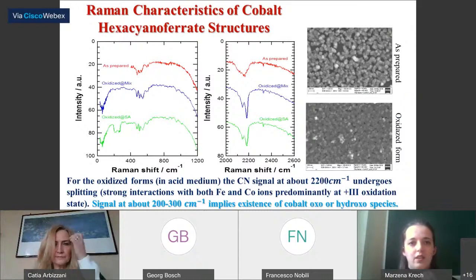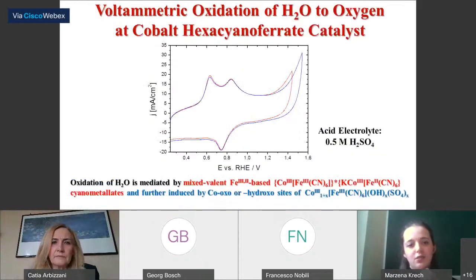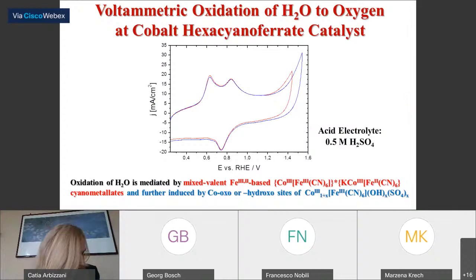These structures are confirmed by Raman spectra shown on this slide. For the oxidized forms in acid medium, which is the green curve, the signal at about 2,200 reciprocal centimeters undergoes splitting. It's from the strong interactions with both iron and cobalt ions, predominantly at +3 oxidation state. The signal at about 200 to 300 reciprocal centimeters implies existence of cobalt oxo or hydroxyl species. This graph shows oxidation of water to oxygen at the cobalt hexacyanoferrate layer in sulfuric acid at potentials higher than 1.3 volts.